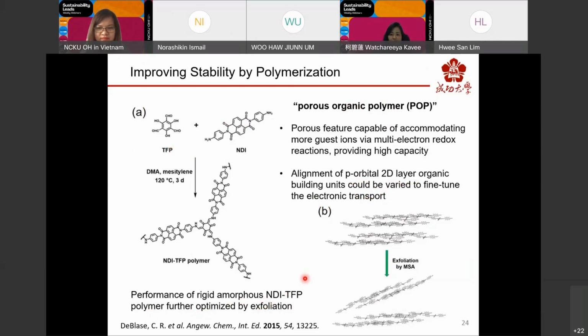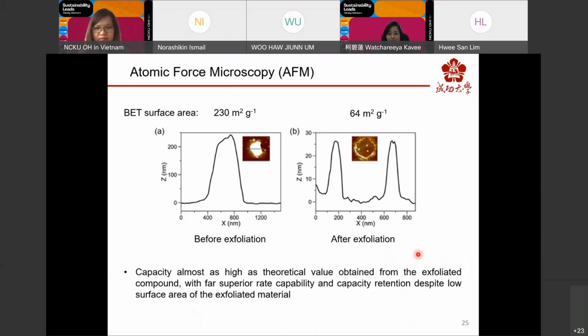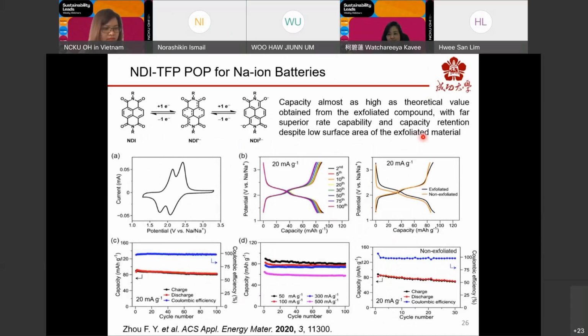Now, the electrochemical performance of the polymer has been further optimized by exfoliation. We also use AFM as well as BET to confirm the exfoliation process. And the specific capacity, almost as high as the theoretical value, can be obtained from the exfoliated compound, with rate capability and capacity retention far superior to the non-exfoliated one, despite the low surface area of the exfoliated material.